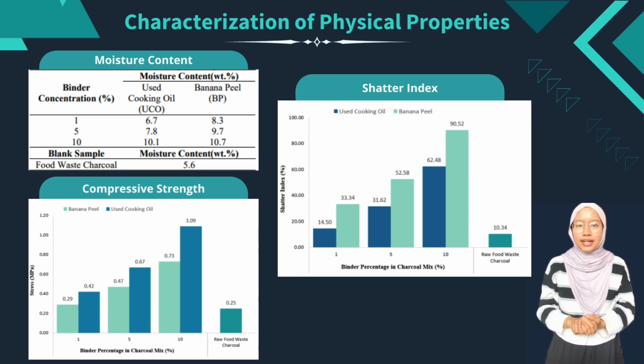For compressive strength analysis, raw food waste charcoal has the lowest compressive strength at 0.25 MPa due to the lack of binders that enhance structural integrity. This implies that the addition of binder enhances the compressive strength of food waste charcoal by improving adhesion between charcoal particles. A briquette containing 10% used cooking oil achieved the highest compressive stress of 1.09 MPa over other mixed samples, as it interacts with the charcoal particles to form a cohesive framework that strengthens the material structure.